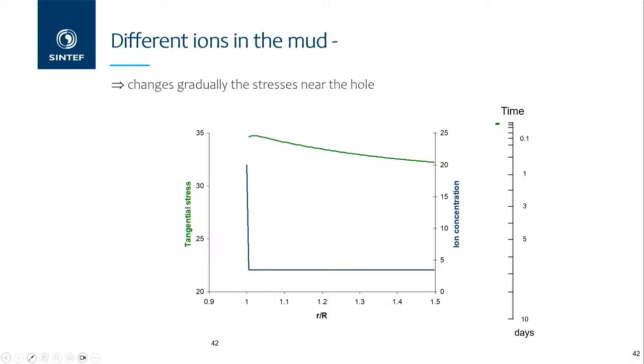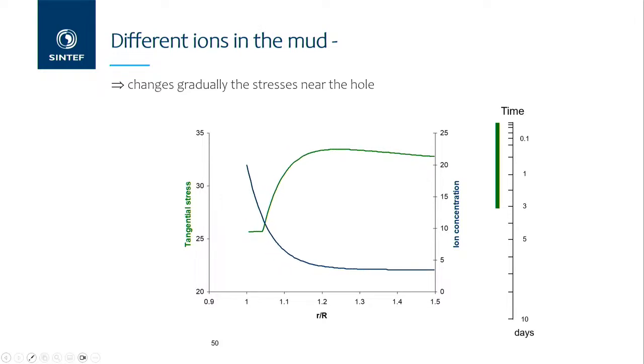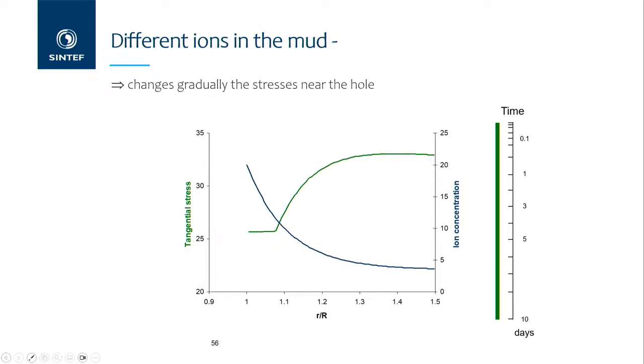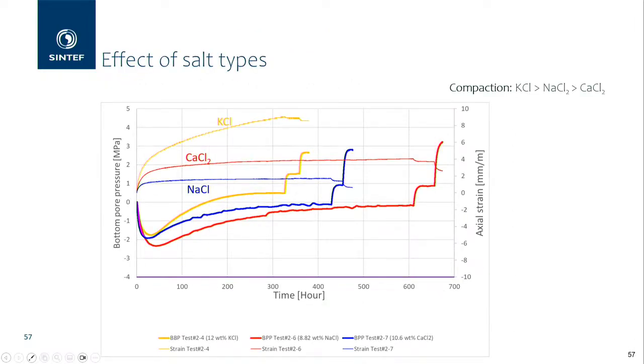When you shrink the surrounding rock, this is the tangential stress, and this is the concentration again, the same. And with time, the hoop stress goes down, and it settles at a number, and then it starts to move away from the borehole wall. Yeah. Okay. So now, if you look at the test result, this is the zero line. Sodium chloride, calcium chloride, and potassium chloride. Sodium chloride is expected; it will not actually exchange a lot of things.